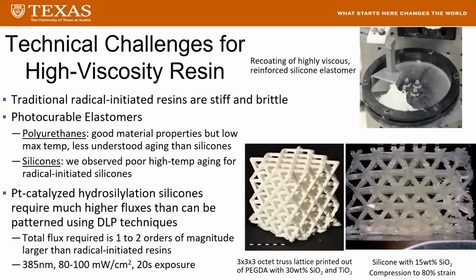We have previously investigated UV curable silicones with a thiolene radical-based curing system, but we observed pretty poor high temperature aging with this chemistry. So we are instead looking into adapting the traditional method of curing silicones, namely a platinum catalyzed hydrosilylation reaction, adapting that to be UV curable. There has been some work in using UV to cure these types of systems, but it's been using relatively low intensities with curing times on the order of minutes, preventing its use in AM.